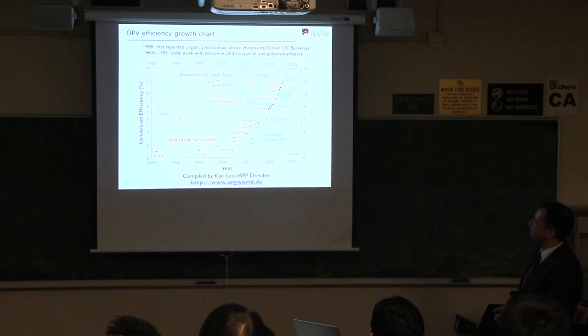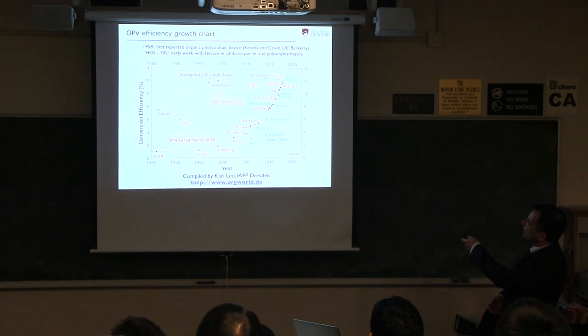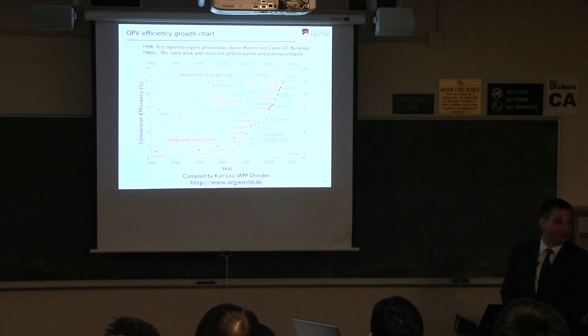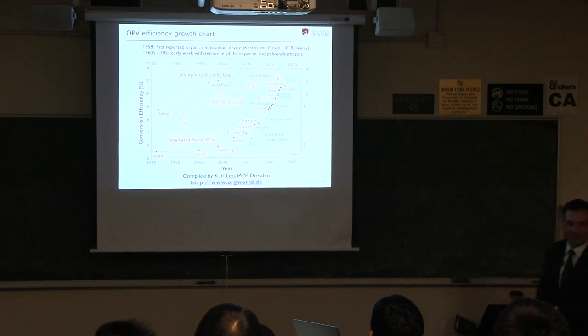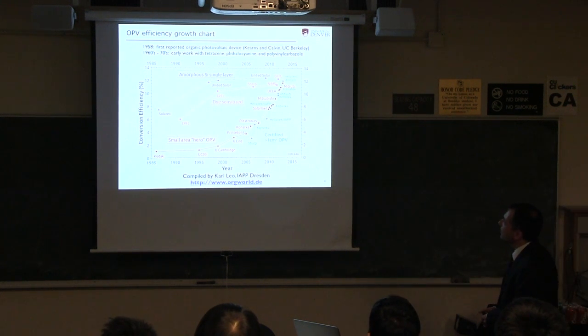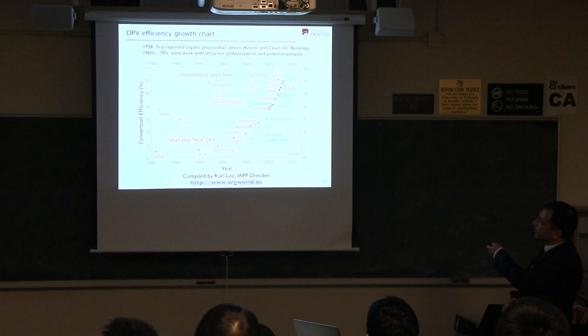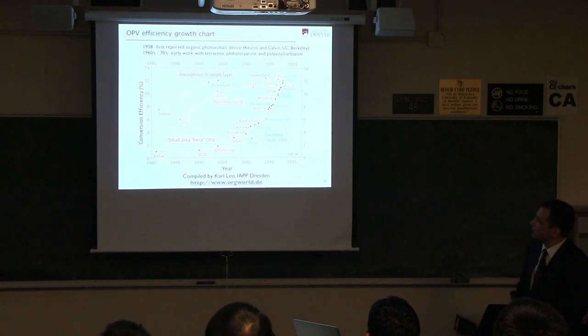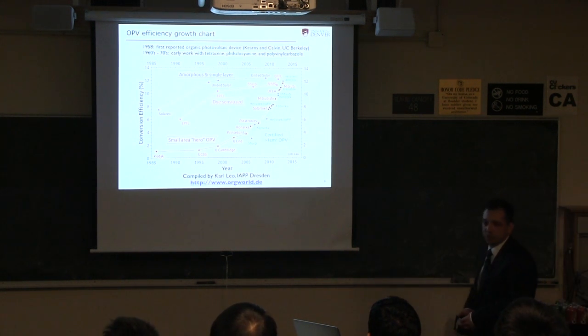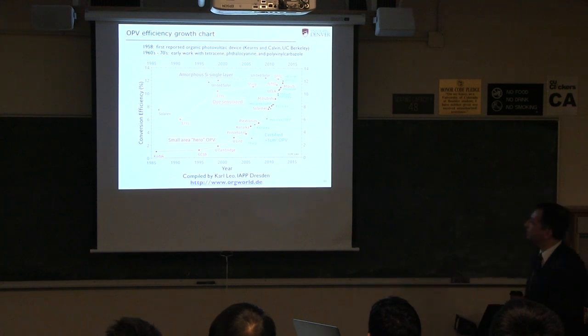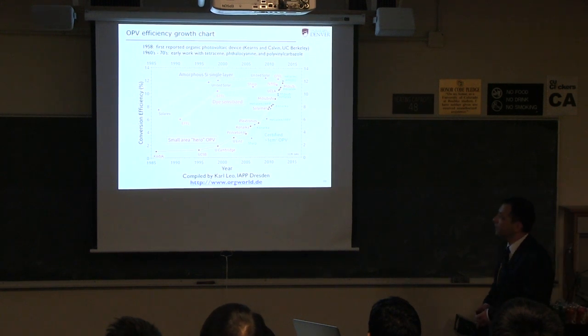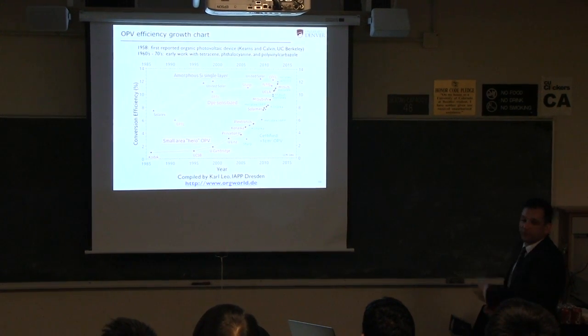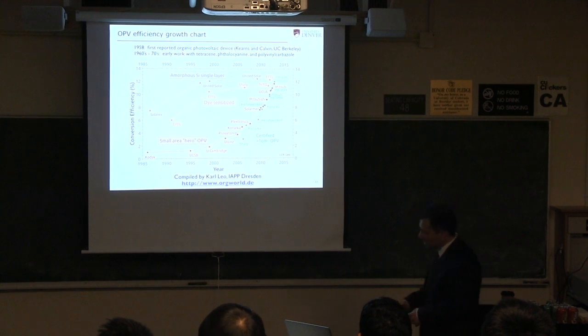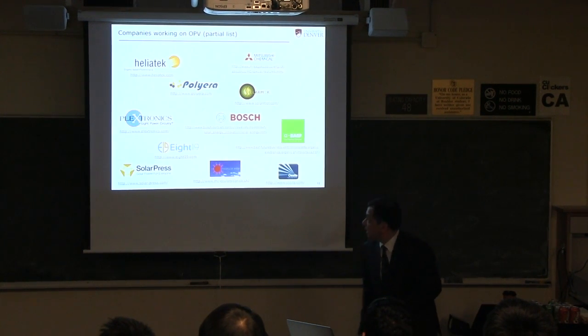And I wouldn't want to do it, but if you extrapolate, you get to some very nice numbers very rapidly. But you know, this has to be a sigmoidal curve and not an exponential. But I just want to point out that the recent numbers are about 12%. And that's the world record, from this German company, Heliatek, based in Dresden. And Mitsubishi Chemical Corporation is close behind them at about 11%, 11.5%. And a whole bunch of universities in sort of the 10% range. So a lot of recent progress.